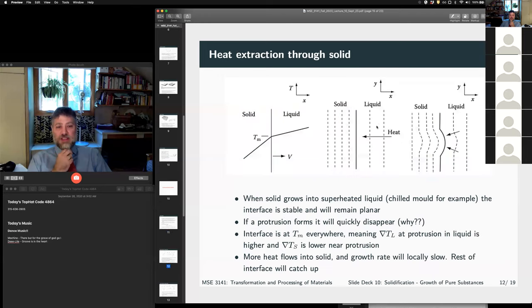So if we have heat extraction through the solid, that means we have some kind of chilled mold, right? Or like ice cubes freezing in a tray in the freezer. We've got a cold sink surrounding our liquid, right? This is also a fusion weld, where the metal surrounding the weld is much cooler than the liquid in the middle, right? And so when we have this, we have a gradient approaching the interface. We have another gradient in the liquid, but right at the interface, we should be very, very near to the melting temperature, right?